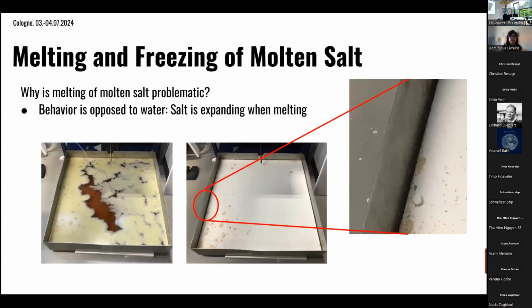And so here are some pictures of molten salt. This was when we drained a smaller oven. You can see on the left picture, this is where we started draining the salt from the oven in a pan. And the right picture is then, I don't know, maybe 1 or 2 days later when the salt was solidified. And here's a very salient feature of molten salt when you compare it to water. It has an opposite behavior when it is freezing. So you can see it here on the magnification on the right, that it is actually shrinking during the solidification process. You can also see it here on this picture that there's a gap forming when this happens.